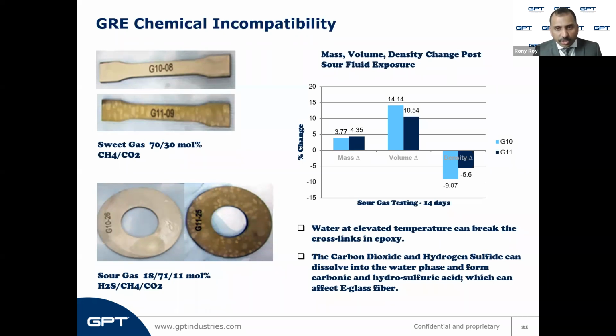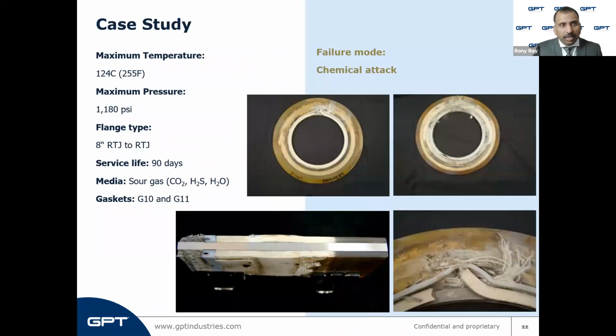We performed mass change, volume change, and density tests on the G10 and G11 samples, and indeed they were both attacked and had significant changes in these three parameters by the sour gas that was introduced into the media while testing. This is a live case of how GRE will fail under conditions of chemical incompatibility in sour media.